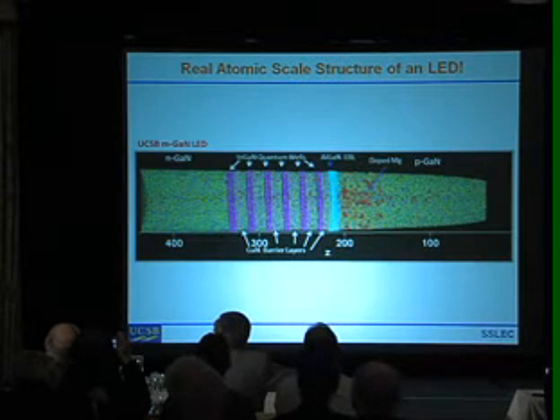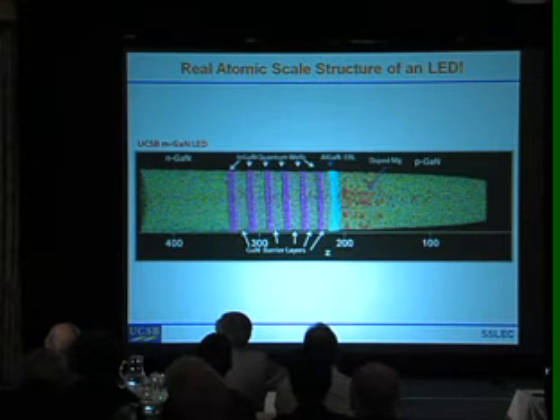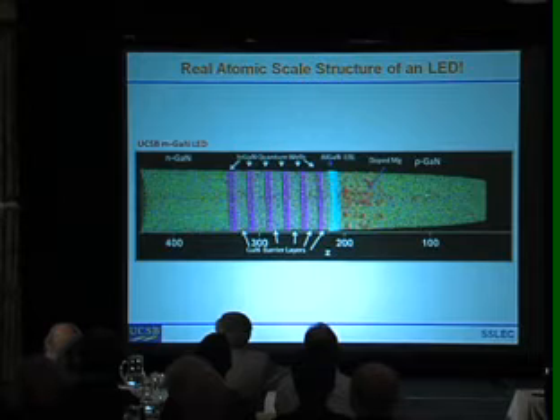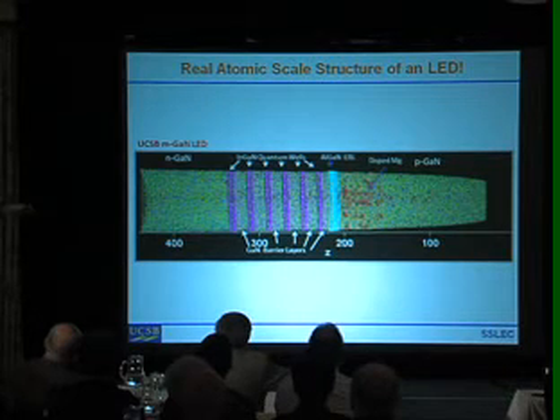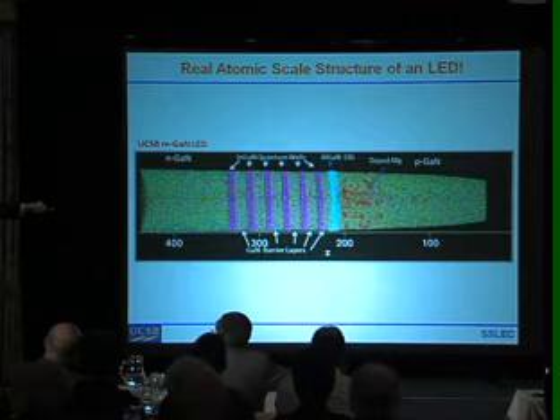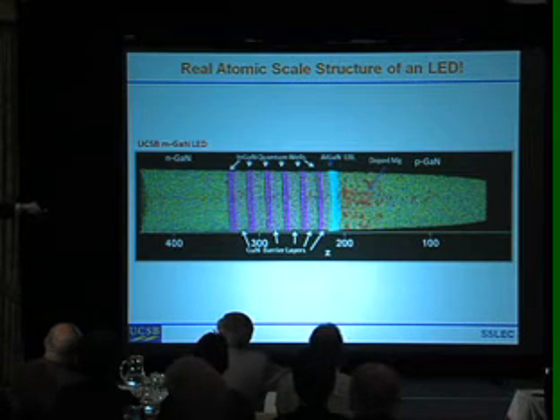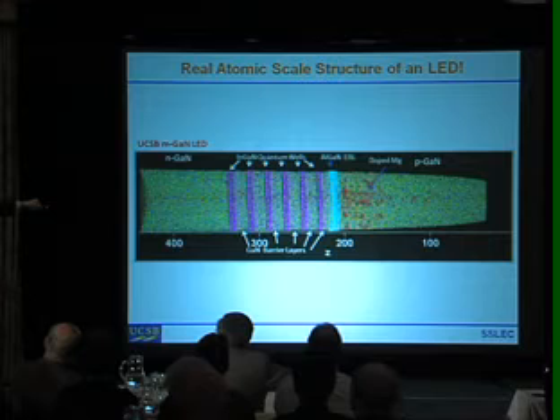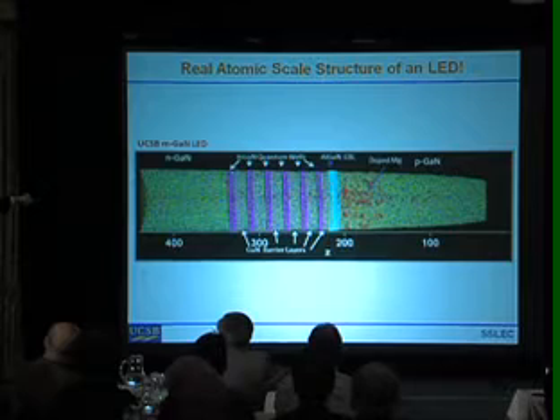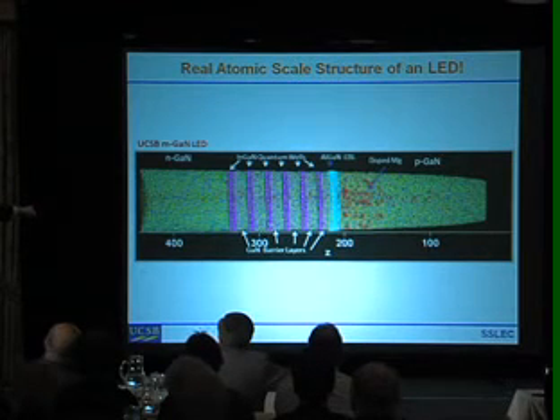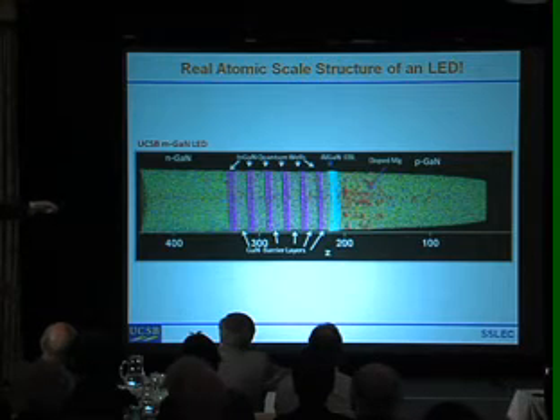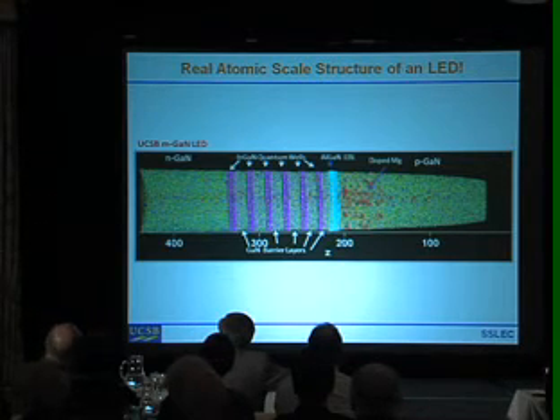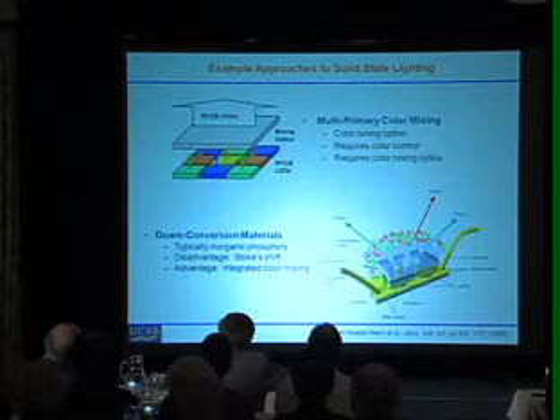And then the real structure of a light-emitting diode looks like this. This is research supported under the SEAM Center at UCSB. This is an atom probe tomograph. This is about 100 million atom data set, actually looking at the atomic structure. So every little pixel in here would be a single atom that we record sequentially. In producing this, this is the P side of the semiconductor where we inject the holes. This is the N side of the semiconductor. And if we do this well in the material with the right energy band gap, so this produces the right radiation of light, and these are the indium gallium nitride quantum wells, this is where we actually produce the light that then we have to coax out of the semiconductor for the solid-state lighting.